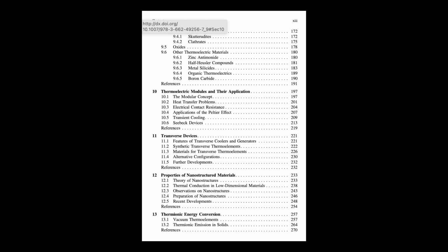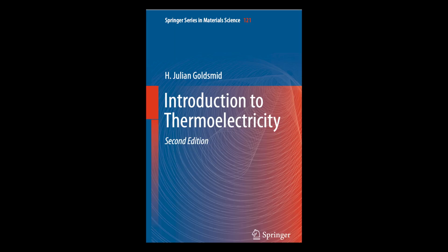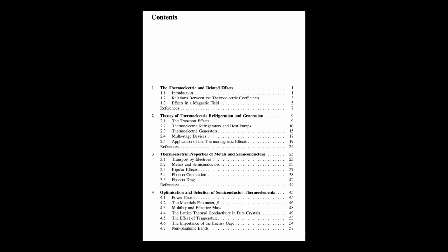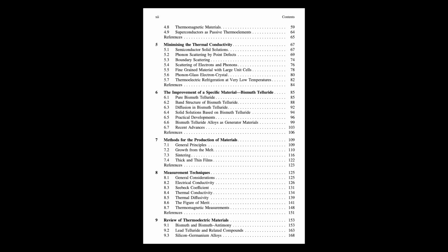And finally, those thermomagnetic coefficients, Nernst, Ettingshausen. What's the setup? For those, you need your sample and a magnet, obviously, and you need to apply either a temperature gradient or an electric current. Then you need tiny, precisely placed voltage probes and thermocouples to pick up the transverse voltages or temperature gradients that appear, often done in a cryostat for temperature control. You usually measure adiabatic coefficients first, then calculate the isothermal ones. There's even a technique developed by Guthrie and Palmer to measure a thermomagnetic figure of merit directly by watching the voltage change transiently after switching on the current. Clever stuff. Incredible detail on the experimental side.